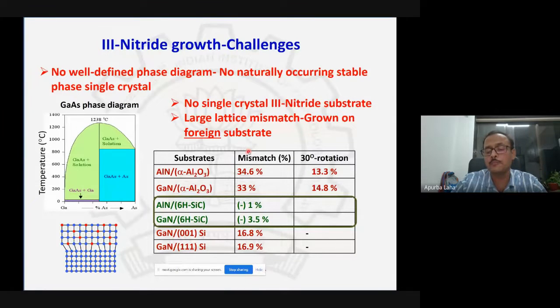If you look at the lattice mismatch between the substrate available, sapphire for example, and gallium nitride, you have more than 30% lattice mismatch, which is hugely high. That is what makes it very challenging. Another available substrate is silicon carbide, which is the most suitable substrate for gallium nitride. But one of the challenges with silicon carbide is that it is super expensive. A 2-inch silicon carbide substrate costs $1,000, whereas a 2-inch sapphire substrate costs $50 to $60. Silicon also has a large lattice mismatch. These are the challenges we have to deal with, and that is why it took quite a long time, almost more than 2 decades, to come up with a useful device.